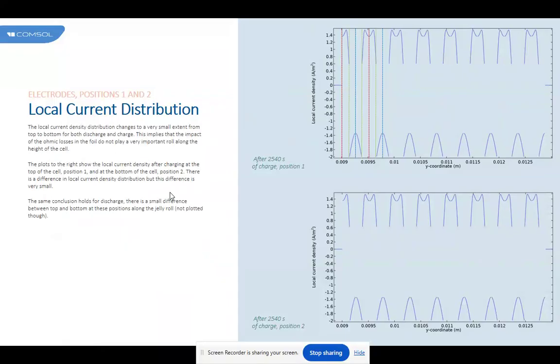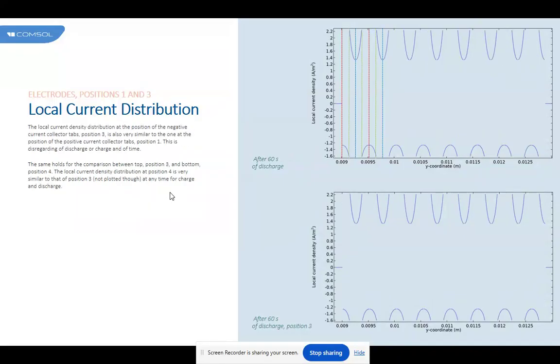Electrodes position 1 and 2, local current distribution. The local current density distribution changed to a very small extent from top to bottom for both discharge and charge. This implies that the impact of the ohmic losses in the foil doesn't play a very important role along the height of the cell. The plots to the right show the local current density after charging at the top of the cell, position 1, and at the bottom of the cell, position 2. There is a difference in local current density distribution, but this difference is very small. The same conclusion holds for discharge. There is a small difference between top and bottom at these positions along the jelly roll, not plotted here.